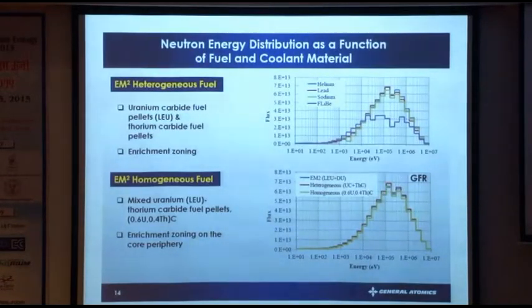Here are the cases that we have investigated. We've investigated two options of fuel loading. One is what we call the heterogeneous loading, and the other one is the homogeneous loading. In the heterogeneous one, there are uranium carbide fuel pellets and thorium carbide fuel pellets, which are separate, and there is also some enrichment zone required in the core.